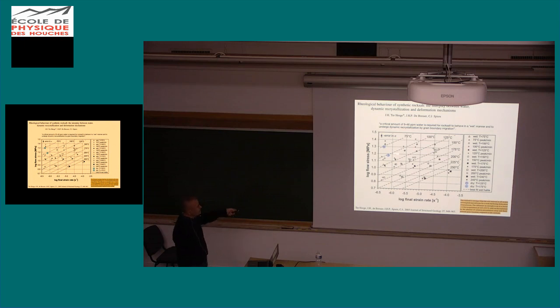The wet samples were quite a lot softer than the dry samples. These two samples here are dry samples, and look, this one is 125 degrees C dry and 75 degrees wet is about the same strength profile, and this one is 175 degrees and the same strength is 100 degrees wet. There is a critical amount of about 4650 ppm water, and that is enough to weaken the salt. So the problem in these early studies was to actually create dry salt.